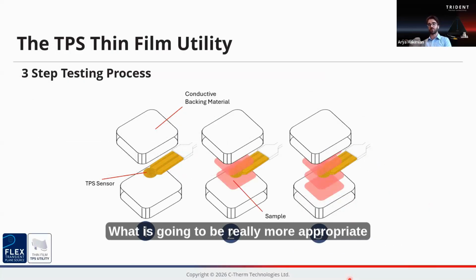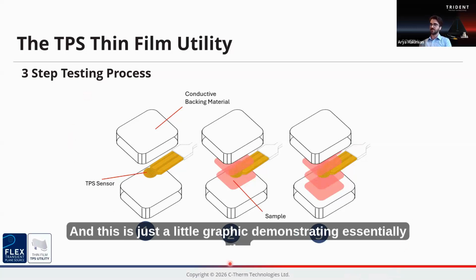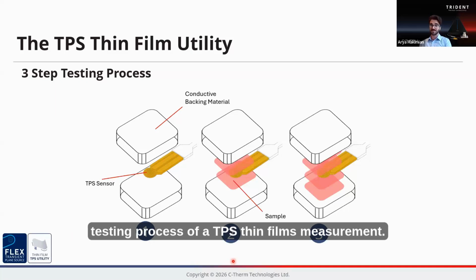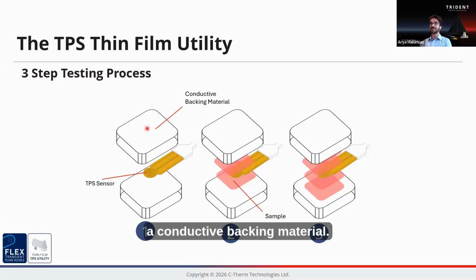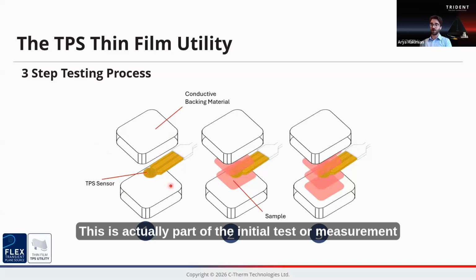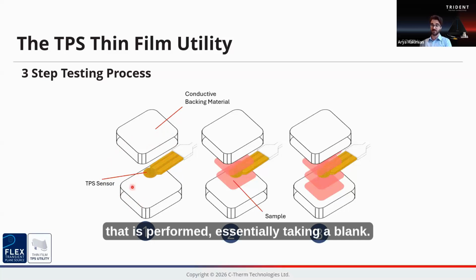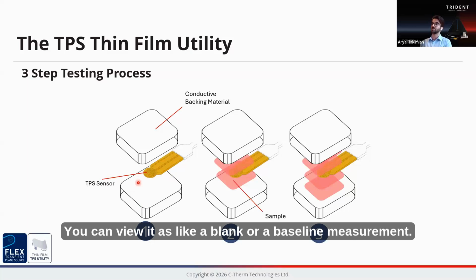What is going to be really more appropriate in this case is the TPS Thin Films Utility. And this is just a little graphic demonstrating the testing process of a TPS Thin Films measurement. It's essentially a 3-point test that is done. You have your standard TPS sensor with a conductive backing material. This is actually part of the initial measurement that is performed, essentially taking a blank. You can view it as a blank or a baseline measurement.